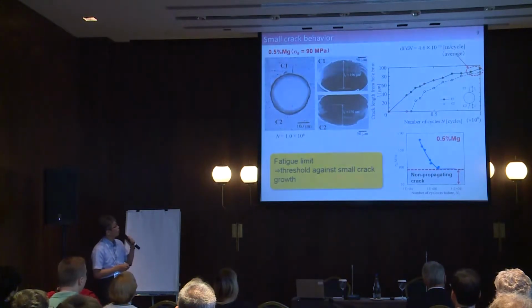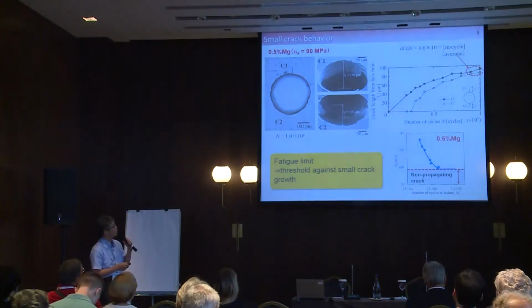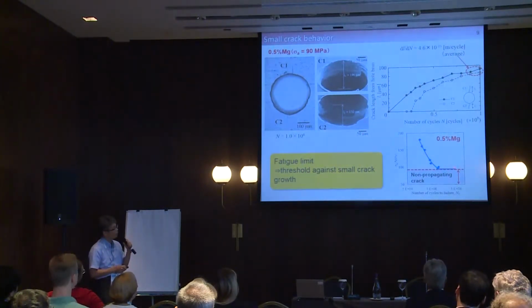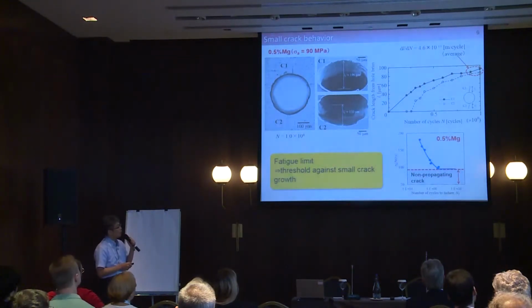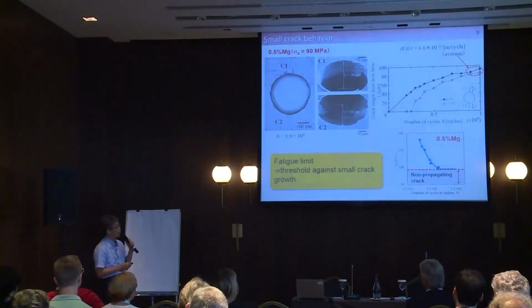And let's see the small crack behavior. These pictures show the small crack behavior emanating from the rim of the hole. When the stress level here, 90 megapascal, is just below its fatigue limit, 95 or 92.5, the cracks initiated from the hole are gradually retarded and almost arrested at the run-out cycles, 10 to the 8th cycles. So we can say that the fatigue limit observed in the new alloy is a threshold against small crack growth.